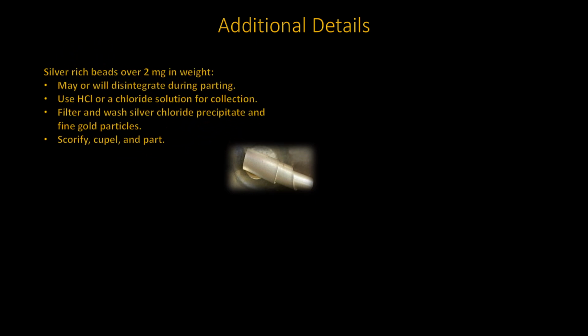There are other considerations that you should be aware of. Silver-rich beads that have a weight greater than 2 milligrams may and will disintegrate. When this happens, not all is lost. Those fine black particles of gold may be collected by adding a drop or two of diluted hydrochloric acid into the parting solution. When the parting reaction is complete, the resulting product is actually a silver nitrate solution.